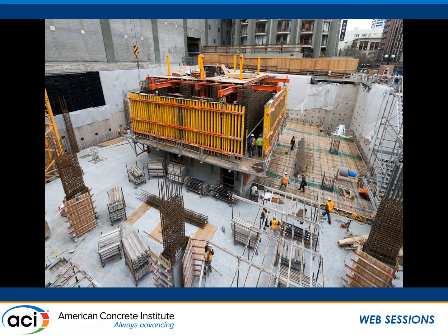But then below grade, we used PT everywhere. And the way we were able to do that and to release the PT slabs from the wall is that the walls were shotcreted. We use shotcrete on the wall after 28 days. So you advance the whole building. You build it as if you're building from a slab on grade, and you advance the building up, and then you come back and shoot the walls. Then you lock in the slab.